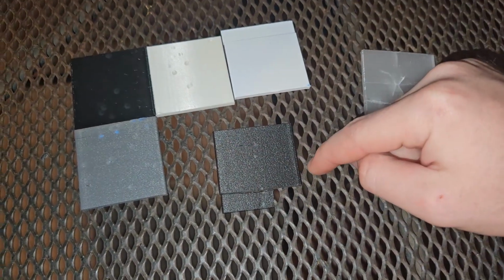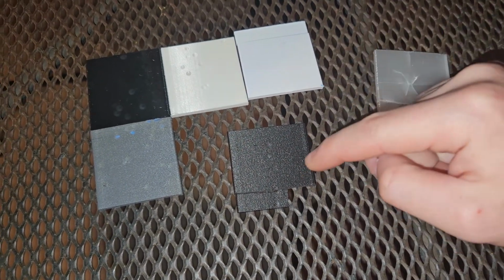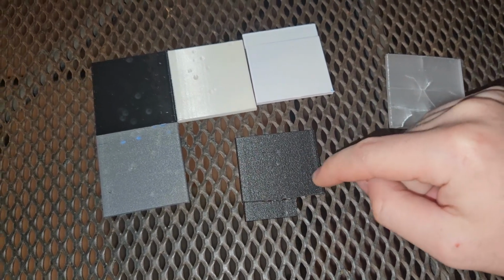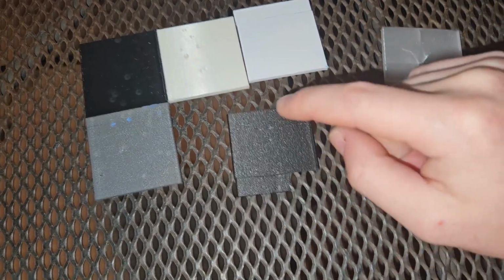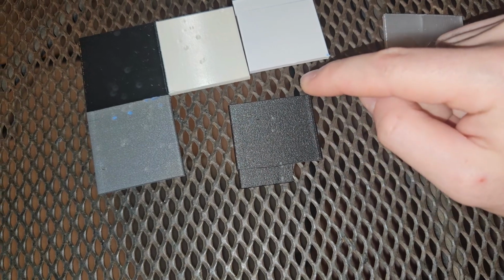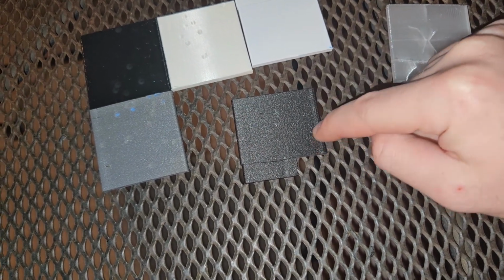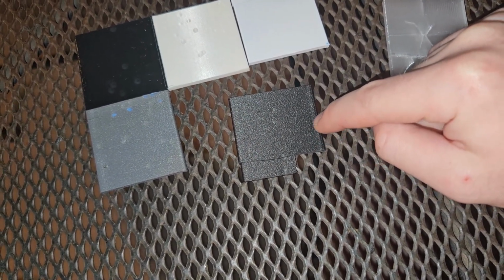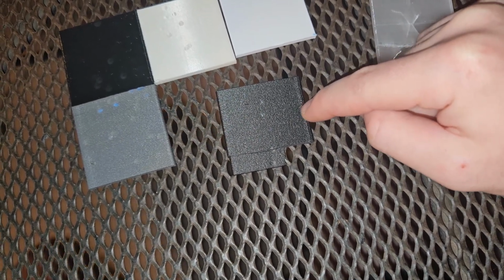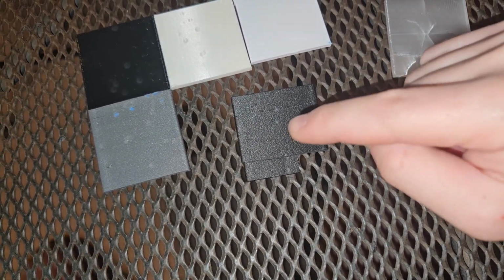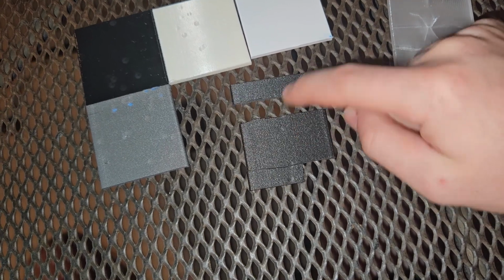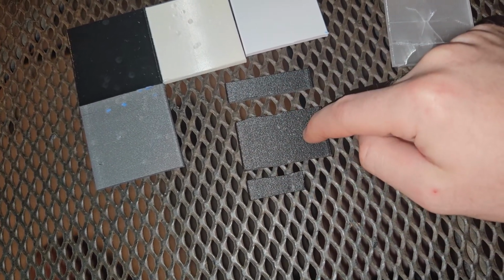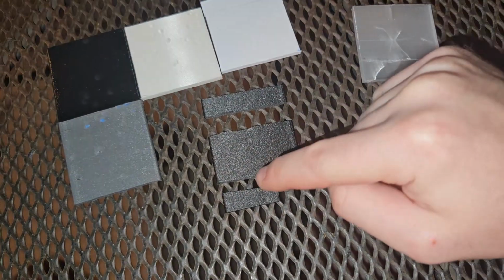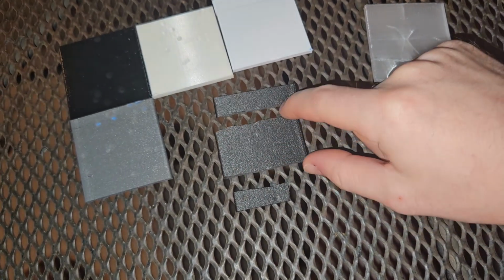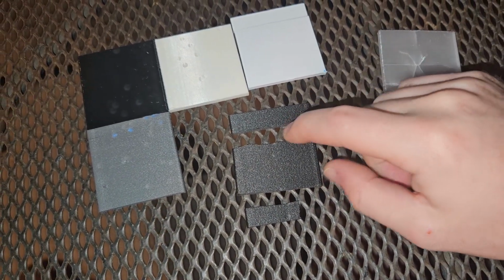Next is this Carbon X EZ PCCF. This stuff's so cool. This stuff prints really, really well for being an engineering grade material. It hasn't warped off my bed. The carbon fiber makes the details really nice and crispy. It's one of the most rigid materials I've ever seen. There's no flex, no give to it. It feels really premium to print. Unfortunately, it survived the first shot, which means it did a little better than PETG, but it broke in more than one place, which I would call a direct fail.